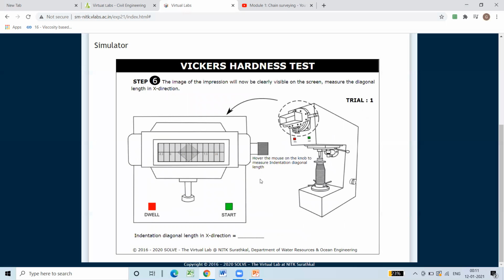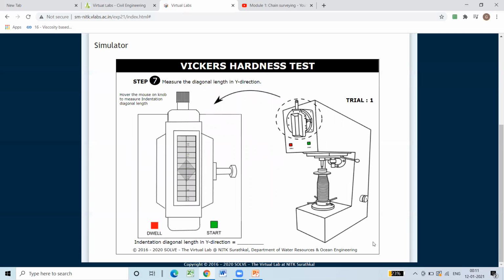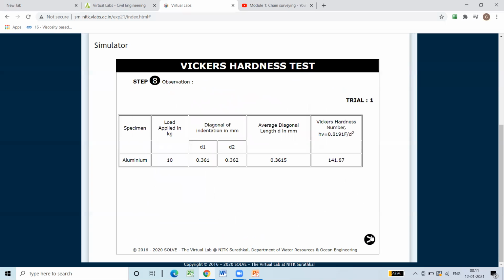In the next step, using the microscope, you just measure the impression formed on the specimen. So here we can see the indentation diagonal length in the x direction is around 0.361 mm. See it for the vertical distance or vertical impression. Yes, it is around 0.362 mm. Now the specimen used is aluminum, the load applied is 10 kg and the average diagonal length will be around 0.3615.